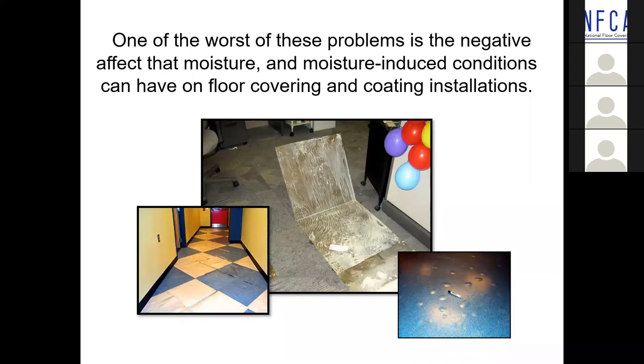Now, when most people look at that picture, what do they say? They say the adhesive is reemulsified, but I want you to know that that is not always an accurate statement. We took water-based adhesives and coated stainless steel strips of metal. And if you do that and allow the adhesive to achieve its proper degree of set, and then you immerse that coated strip of stainless steel metal into pH neutral water, pH 7 distilled water, it doesn't reemulsify.